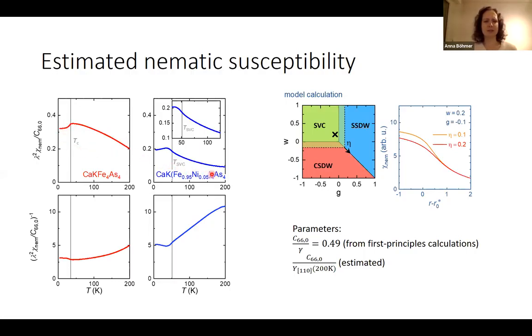The nematic susceptibility in our doped 1144 increases in a Curie-Weiss-like manner, but is far from critical. Remember, this has to be 1 at the transition, so we are much below that. Then at the transition, there's this subtle anomaly that almost looks like an inflection point, or it does look, there is an inflection point here. And it's tempting to compare that with our model calculation, where in the case of a finite eta field, which we have in these compounds, there is also predicted to be an inflection point of the nematic susceptibility at the transition here. So to make the connection becomes tempting.